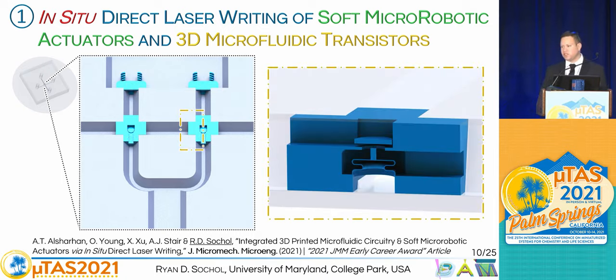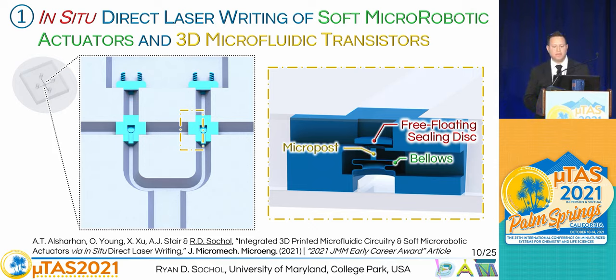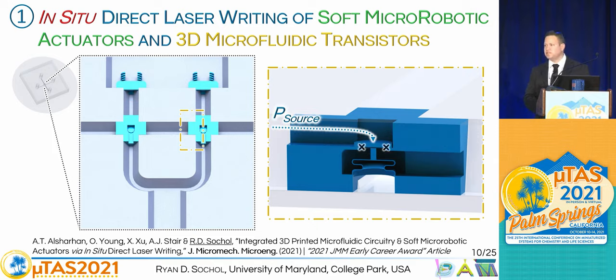And so this is a cross-sectional view, and there are a couple key components here to understand the functionality. One is that we have a free-floating sealing disk. And so I mentioned the speed of this technology, and because of that speed, we're able to print this completely in midair without any types of support structures you would typically see using 3D printing. We also have this bellowed microstructure that has this micropost on top. So initially, when there's a source pressure, it's able to shift this disk down to seal atop the orifice and block fluid flow through the component.